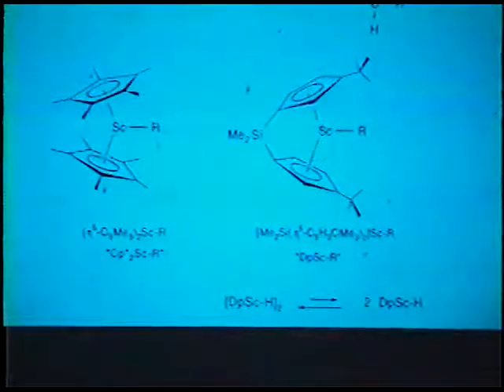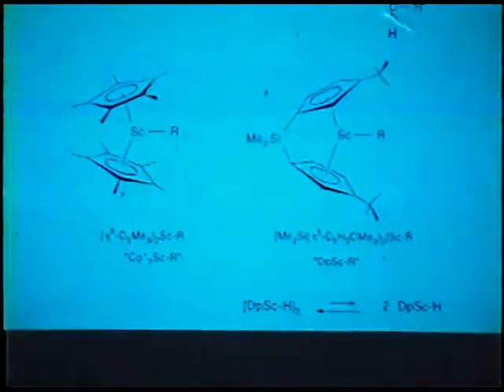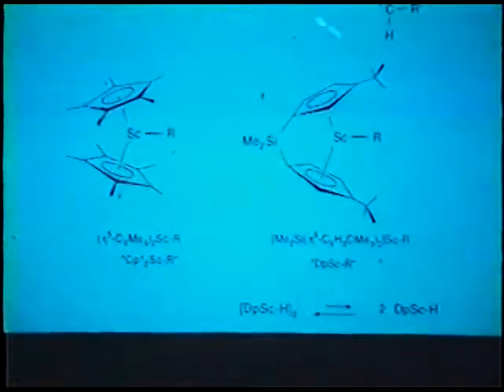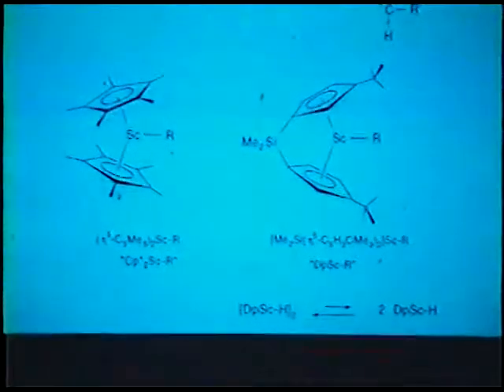And so the olefin turns and approaches this equatorial plane with the CH bond, and that's just the reaction centered at the carbon-hydrogen rather than this carbon-carbon double bond. Well, if that's true, if we take some of the sterics away, maybe we could see some chemistry of alpha olefins with these scandium alkyls. And so we prepared a number of less crowded versions of these scandium complexes. And here I show you the results from a system that's been tied back with a silicon bridge to open the way. What we find is indeed alpha olefins do react by a process other than sigma-bond metathesis. In fact, they are nicely dimerized, and very highly selectively dimerized in the case of butene to this head-to-tail version.